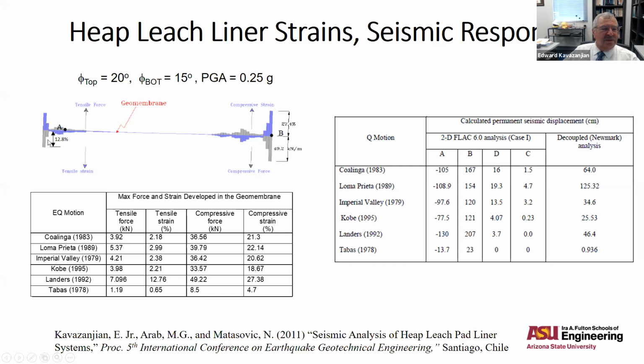And here the tension is shown in gray. We also get some compression as the waste shakes back in the other way. And on a downhill side, we get slightly greater tension. Most of the time, the tension was pretty manageable. We used six different motions. For five of the motions, the tensile strains due to seismic shaking were 2 to 5%. But for one case, the Landers earthquake, we had some very high tensile strains. So that's what's shown here, the results for the Landers earthquake with tensile strains on the order of 12%, which is getting pretty close to yield.